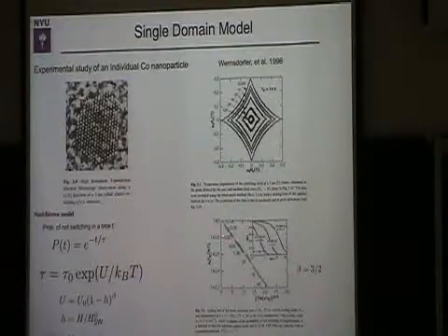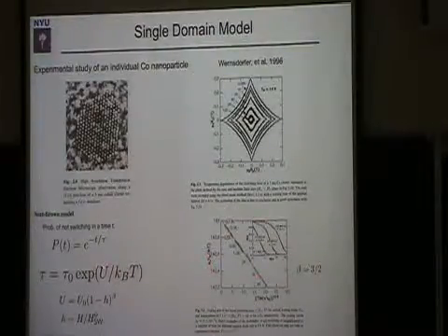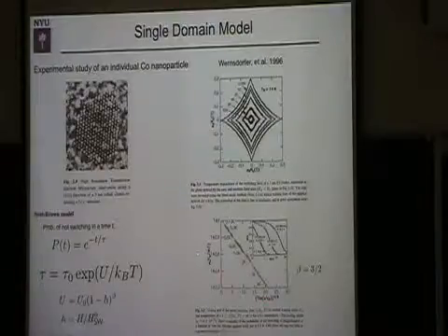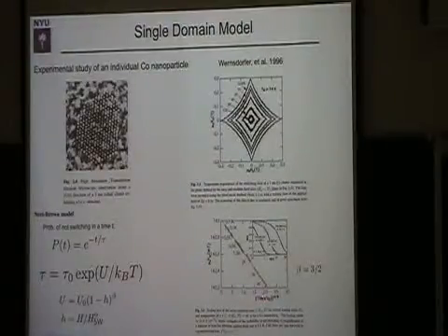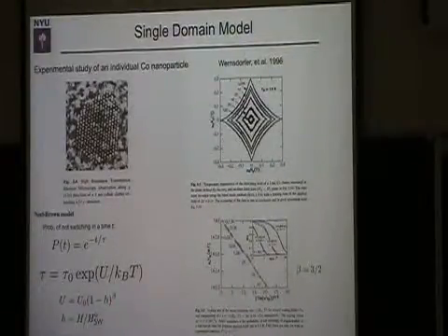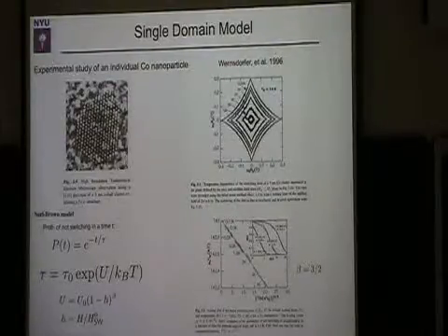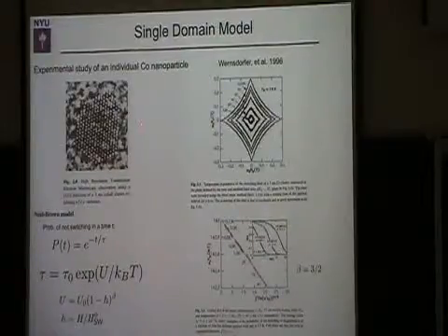And this is the mean of the switching time versus the field at which you're sitting. Based on this model, this is the expected scaling, if beta is 3/2. Beta is 3/2 if the field is not along any of the principal directions, if it's not along the z direction, for example. This was the first example of single domain behavior,